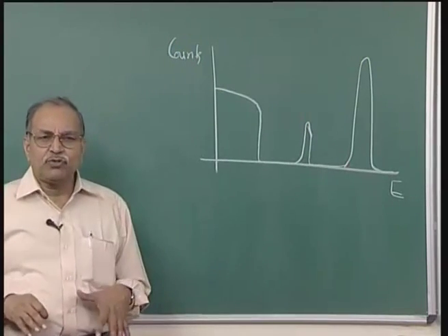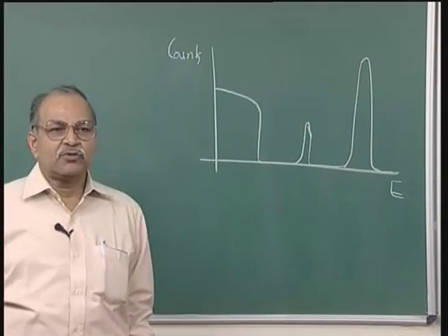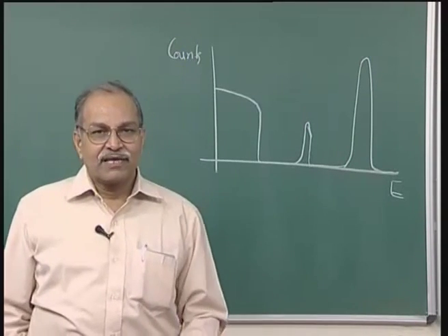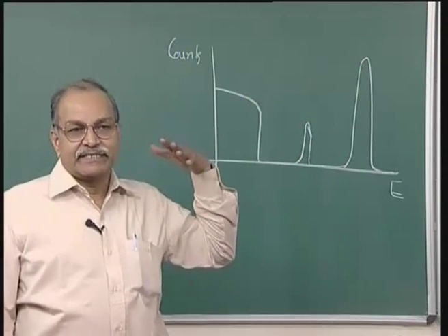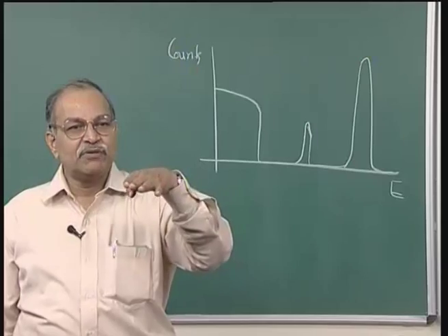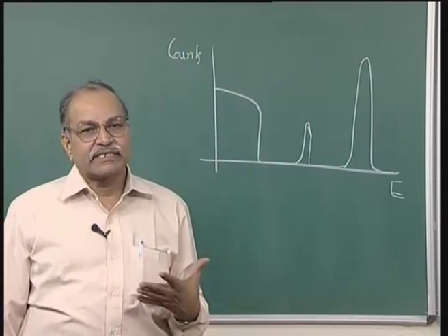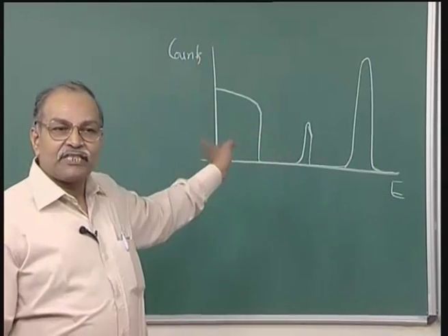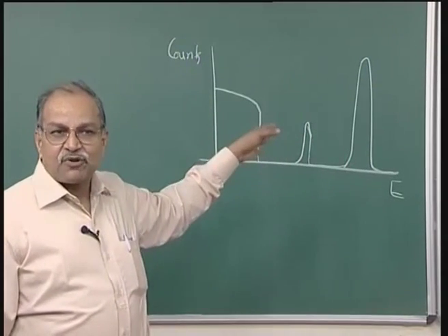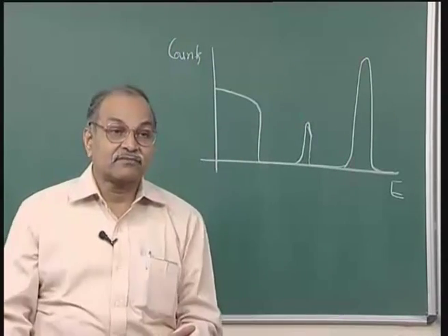Even if I do not know anything about the composition of the sample, I do not know what that sample was, and this is the spectrum given, and I am told that the incident alpha particle is 2 MeV, and the angle theta is this much, 160 or 170 if that is given. I can work out from where all these peaks are coming, where all these spectra are coming from, and what kind of sample that is.